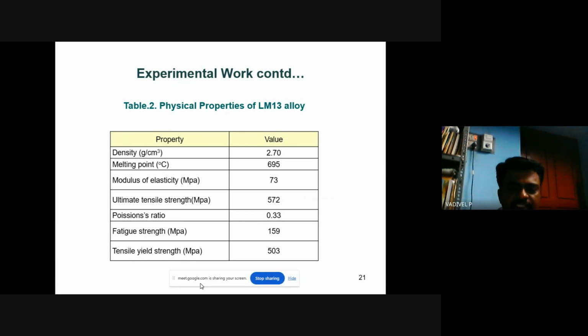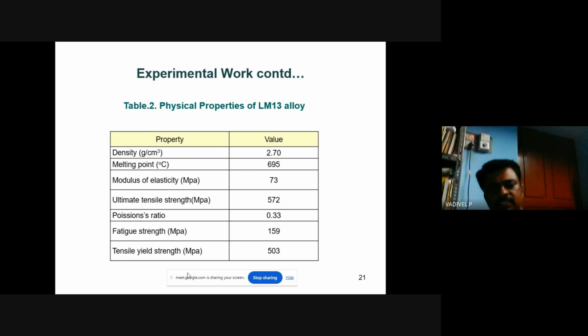The physical properties of the LM13 aluminum alloy: it has a density of 2.7, and the melting point is 695 degrees Celsius. The modulus of elasticity is 73 megapascal. Ultimate tensile strength is 572 megapascal. The Poisson's ratio is 0.33, the fatigue strength of the LM13 aluminum alloy is 159 megapascal, and the yield strength is 503 megapascal.